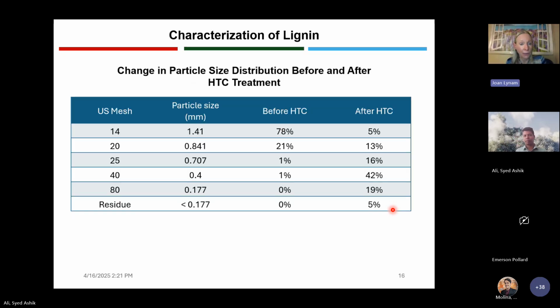All right, we meshed these things to figure out what particle size we have. You can see that before we did hydrothermal carbonization, we tended to have pretty big pieces of solid, but afterward, we mostly had smaller particle size pieces of lignin. We're talking about 0.4 millimeters to 0.2 millimeters as the main area. So it's around, I don't know, 0.5 millimeter after you've done hydrothermal carbonization on it. Good. We can go on to the next one.